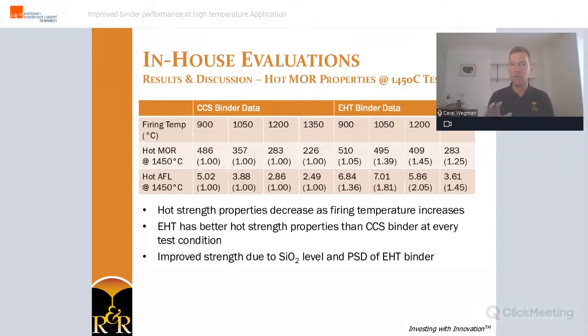So let's take a look at the raw data. This is the hot MOR data from all four different firing temperatures, but tested at the higher temperature of 1450 degrees C. Also here, we normalize the data in brackets against the CCS value. And the trend that's shown here is that the EHT binder has a higher hot strength value at every test temperature compared to the CCS binder. Actually, at a test temperature of 1200 degrees C, it's even double compared to the CCS binder. So we believe that this increased strength of the EHT binder is due to its unique SiO2 level and particle size distribution.